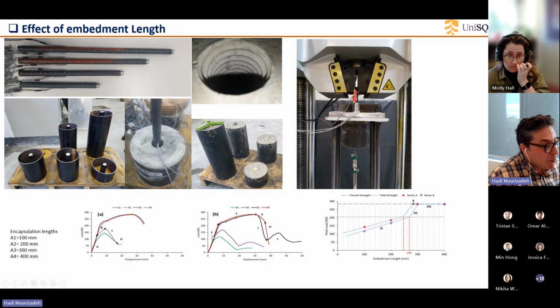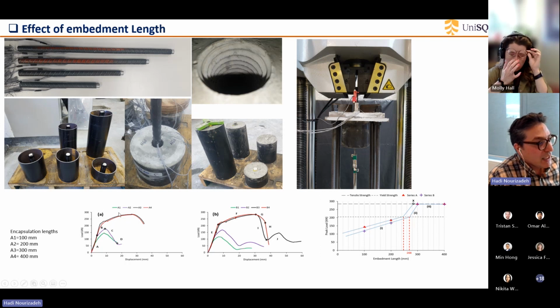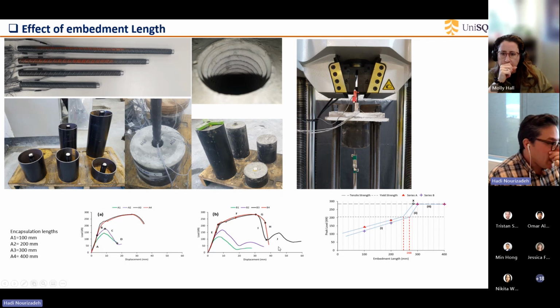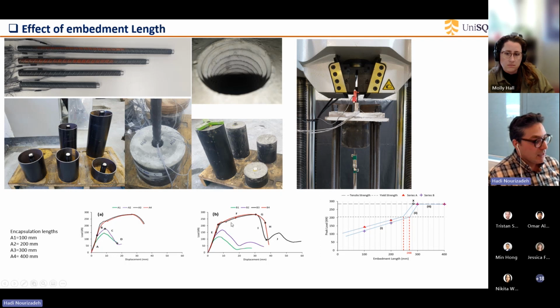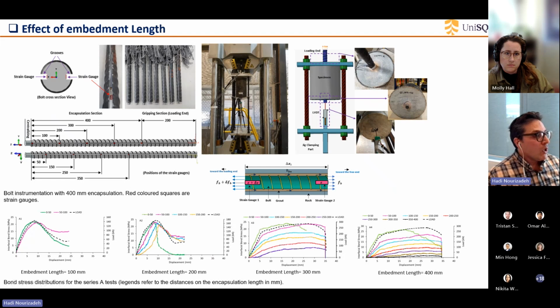So we had the bonding of the sample B3 with the 300 mm. By analyzing the result, we determined the embedment length for both of these samples. For example, for bonding agent A, the critical embedment length is around 250, and for bonding agent B, the embedment length is 268 mm. So generally speaking, it shows that the embedment length is influenced not only by the bolting and the inserting rod, but also by the encapsulation agent as well.